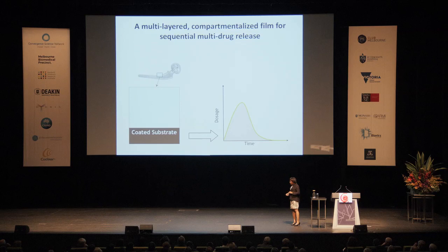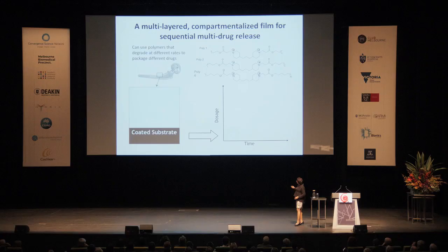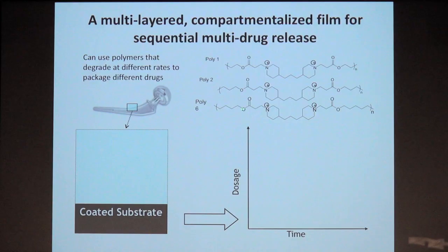With layer by layer, instead of getting, let's say, 1 weight percent or 1/2 weight percent of drug into the film, I can actually layer different drugs with different polyelectrolytes. These are charged polymers that degrade at controlled rates. And in fact, I can control the relative rate at which the polymer degrades by changing the molecular structure.